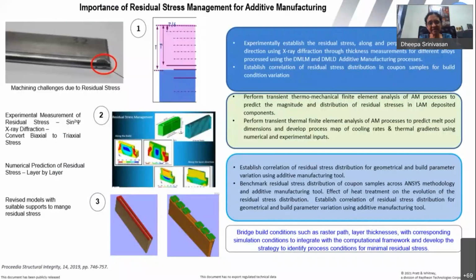See, for residual stress evaluation, there is X-ray diffraction, sin²ψ, or there is neutron diffraction, which is not very easily accessible, though in neutron diffraction the penetration depth is a little bit more. But the fact of the matter is residual stress experimental measurements are only through thickness. That means it can go from the surface to the bulk on a flat sample, but it will only give you surface values or up to a few microns. So you need to keep on removing material. However, that is only the experimental validation at coupon level to qualify your process parameters. It says nothing about the geometry.